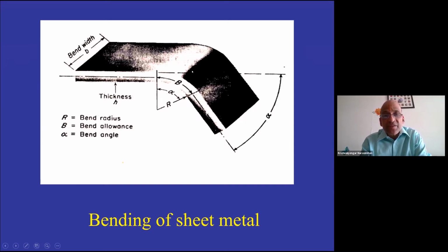Across the bending radius, you will have variation in the stress state from tensile to compression across the sheet thickness, which means the corresponding stress state also will vary from tensile to compression as you go from the top surface to the bottom surface. This is very important to appreciate because many spring back problems are related to this through thickness variation in the stress state, namely from positive to negative side. Hypothetically, if you can imagine that across the thickness our stress state was only tensile, then your spring back issues will be reduced.